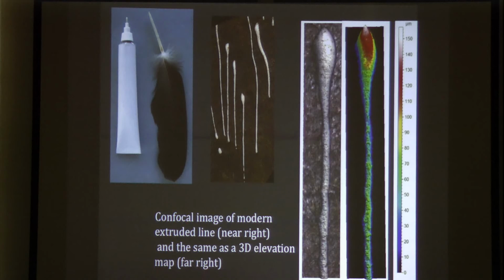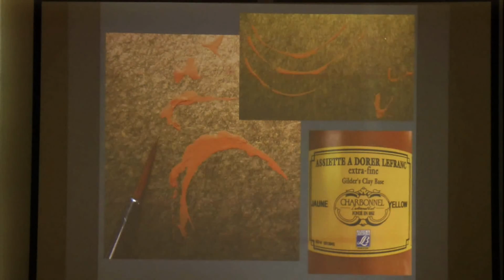The image on the right, those are two different stitched images from our confocal work where we're looking at our mock-ups and not finding out anything great, but I just want to point out that it's pretty irregular. And again, no matter how hard we tried, you'd start the line, there would be a heavy deposit right in the beginning. And it was really almost impossible to eliminate that feature. So brushes didn't work. You couldn't get the turnover properties of that.